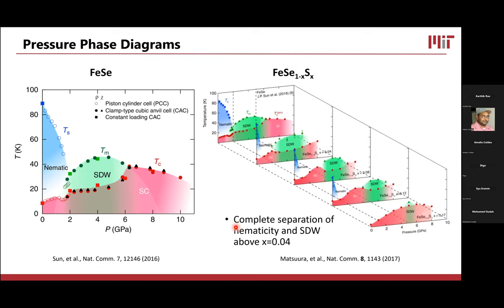It's complicated further by looking at the evolution of iron selenide with sulfur doping and with further pressure. So if we look along this axis here, this is the zero pressure change in the phases with increasing sulfur content. Sorry, it's a little bit hard to see, but this is sulfur of 0.04, so 4% sulfur, 8%, 12%, and 17%. So the nematic transition at ambient pressure is suppressed with increasing sulfur doping. It disappears somewhere between 12 and 17.